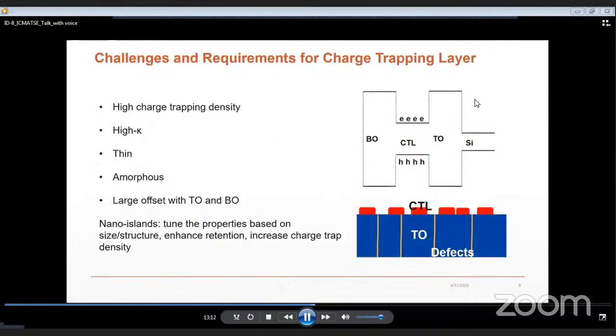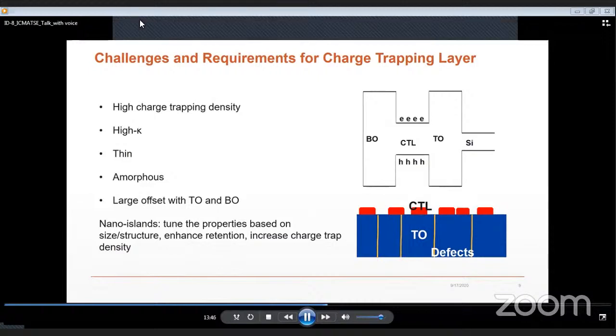Now we move to the requirements of the charge trapping layer. So the charge trapping layer has to have high charge trapping density in order to allow for a large memory window. The charge trapping layer should have a high dielectric constant because this results in a higher electric field across the tunnel oxide and thus allows to achieve the same memory window at lower operating voltages. As for the tunnel oxide, the charge trapping layer is preferred to be amorphous in order to reduce the charge leakage probability. Also, this layer should have a large band offset with the tunnel oxide and blocking oxides in order to better confine the stored charges and therefore improve the charge retention characteristic of the memory.